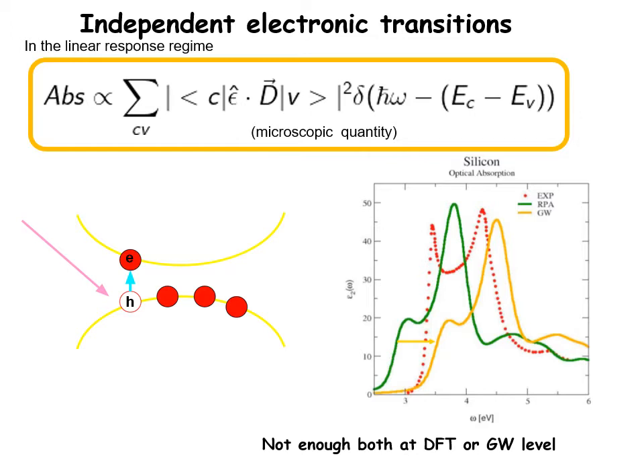From the lecture on linear response theory we have seen how, at the independent particle level of approximation, the absorption turns out to be proportional to a sum of independent electronic transitions from occupied to unoccupied states, obtaining an expression that is nothing else than the famous Fermi golden rule that you have probably learned in your master courses on quantum mechanics. But now you should be aware also of the fact that using this expression to calculate the spectrum of a bulk material like silicon, both at the DFT or even at the GW level of approximation, you are not able to obtain a good description of the experimental curve.